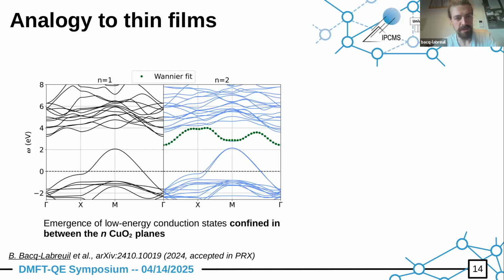So here is the band structure of the one-layer compound and the two-layer compound on the right. These are bulk systems, right? If I just say one- or two-layer compound, it's a number of consecutive planes, but they are really a bulk system. The only difference you see between the two is this extra conduction band, with some dotted points on top, which in the n=2 compound lies quite below the rest of the bunch of spaghetti of the conduction bands.